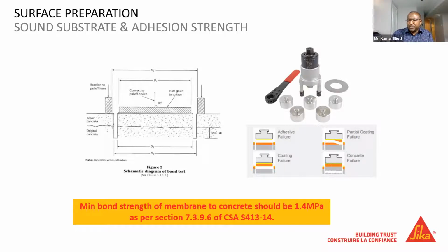We want the bond strength of the system to the concrete to actually exceed the tensile strength of the concrete. So if we were to pull it all off, we want the concrete to be the weakest link in that scenario. And you can see here a reference to the CSA S413. They recommend a 1.4 MPa minimum tensile strength and bond strength to the concrete.